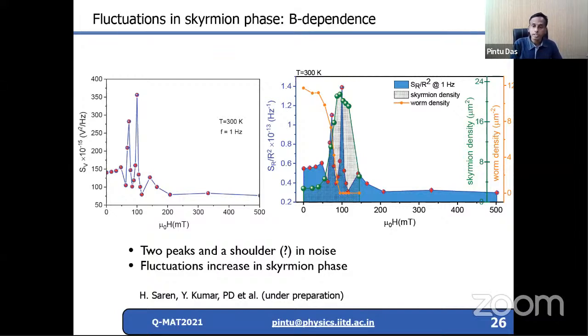So this is interesting from the point of view that it shows that the fluctuation is increasing in the skyrmion phase. However, the fluctuation is showing a peak also in the worm and skyrmion mixed phase, but it is coming down again in between as the skyrmion is developing. So we are not able to understand the data yet. We are still looking at these data, but we have checked the reproducibility. So these are perfectly reproducible data.